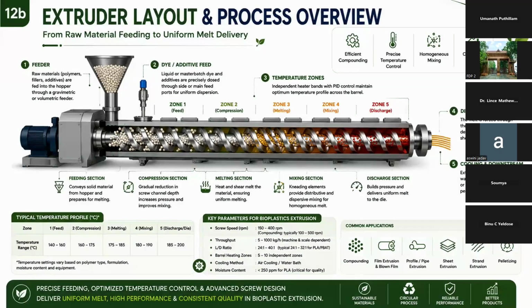And this slide shows the extruder layout and process overview. In figure one, we can see the feeder. In that feeder, as I mentioned earlier, we can use both polymer pellets and powders, so it can work with both. It is fed into the feeder and moved to the extruder. In the extruder, there are different temperature zones, and after zone 5, it comes out through a die, and that is again fed to air cooling or water cooling, and then the pelletizer.